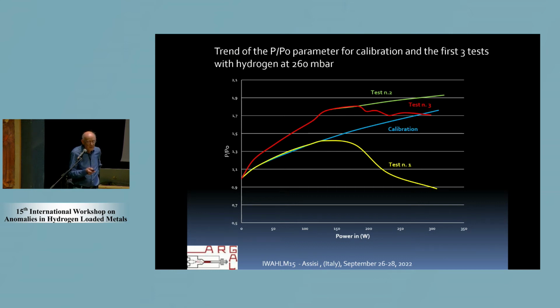At the end of the experiment, the pressure and environment temperature was higher than at the beginning. So I made a third test with the same hydrogen, without changing it, to try to make absorption of hydrogen in the range of temperature from 500 to 700 degrees. You can see the red curve, the operation to go directly to those temperatures was a success, having a reabsorption of the hydrogen.